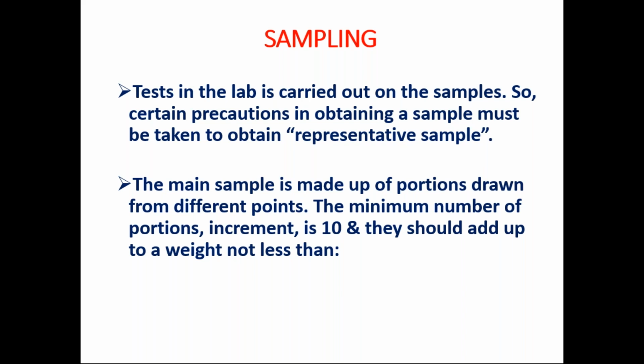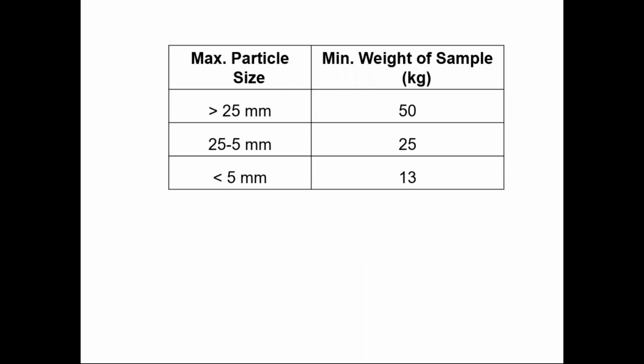The main sample is made up of portions drawn from different points. The minimum number of portions or increments is 10, and they should add up to a weight not less than the following: for greater than 25 mm, about 50 kg; 25 to 5 mm, about 25 kg; less than 5 mm, about 13 kg.